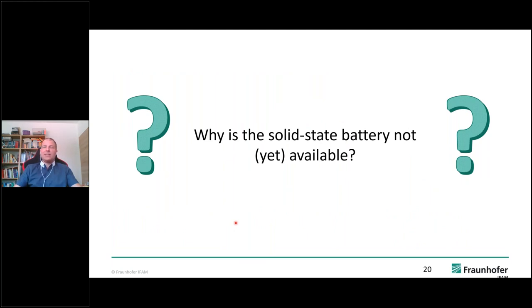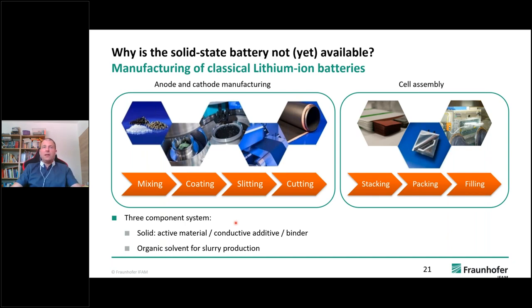And this is also directly leading to the last point: why is this not ready yet? Why can I not use it at the moment, although the materials are already there? And as I said already, the manufacturing has a big part of that. The manufacturing of a classical lithium ion battery starts with mixing of the solid compounds, active material, carbon conductive material, polymer, inside of a high shear rate mixer with a solvent, making a slurry, which is then casted onto metal foils and cut into these round cylindrical shapes, where we get an anode and cathode, which can afterwards be cut out and stacked in the cells, wrapped with a separator, which is the white one, and you can see the copper and the aluminum in the back from the anode and the cathode put on top of each other.